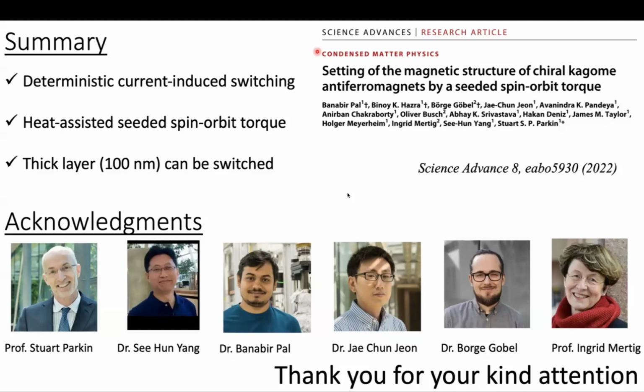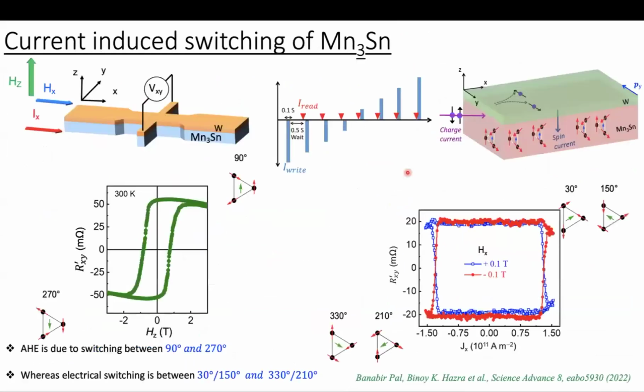Okay. I have another question. In the current induced switching measurement, you were talking about mainly the 30-degree and 150-degree domains contributing. I wonder what happened to the 90 and the 270 domains. What are they doing during the current induced switching? If you look at the torque from these domains, there will be no contribution from them, and that's why the 90 or 270 domains don't contribute to the current induced switching.